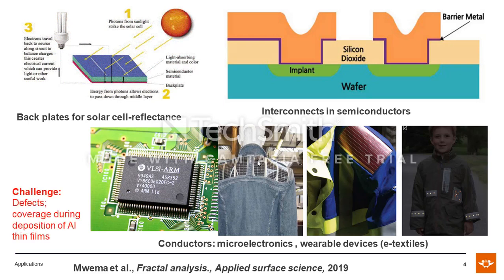Now, the biggest challenge in depositing aluminium thin film is the defect and the coverage. It is difficult to achieve a uniform film, and we have been able to do a lot of work on sputtering to just evaluate, based on the equipment we have, which combination of properties or parameters can give defect-free and more uniformly distributed film. We have done a detailed fractal analysis of defects such as ALOX, and you can find our paper published this year in 2019 in Applied Surface Science.